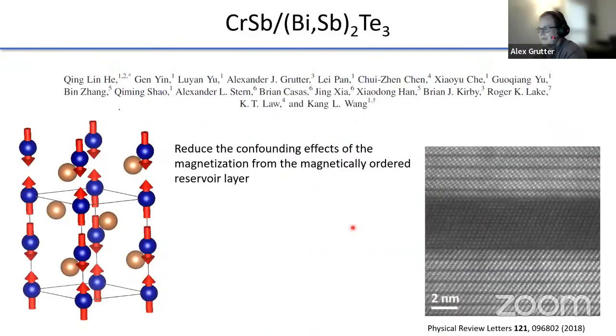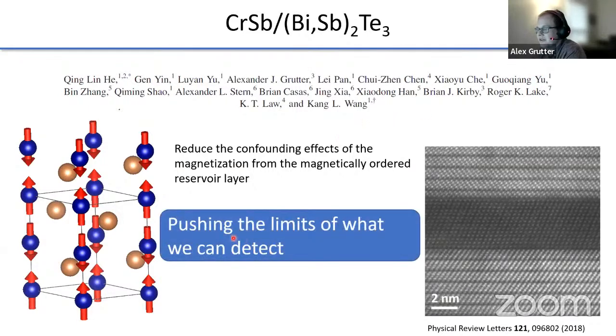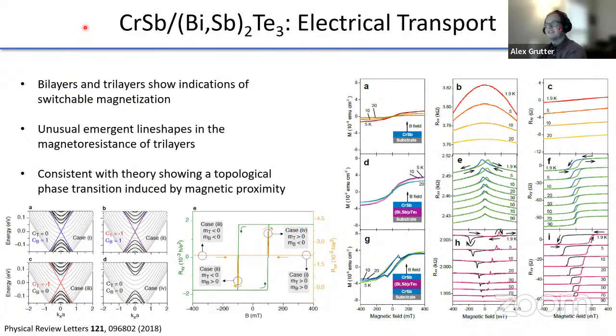Now, I want to finish up the examples section with one final case. This is a case where we're really pushing the limits of what we can detect. And this is another antiferromagnetic proximity effect. It's chromium antimonide, where you again have these spin polarized layers in your sample. And we're going to grow that next to bismuth antimony telluride. This is work led by Qinglin He from Kang Wang's group once more. And you get these really nice high quality interfaces and some really strange electrical transport behaviors.